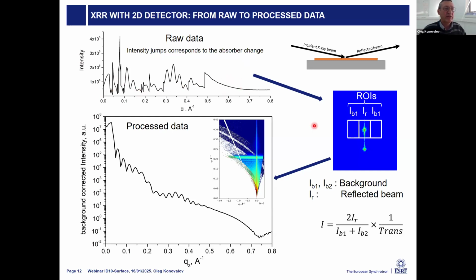And then at each point, we measure now with the two-dimensional detector. On this detector, you can see this is the rest of the direct beam, and this is the specular reflected beam. This is what we really want. Then we select several regions of interest, like 1 for the specular beam and 2 for the background. Through this formula, normalized on the attenuation of the filters, we can reconstruct the reflectivity profile. Everything is done almost at the same time at the beamline. After measurement, we can immediately run the scripts on Slurm, on the special machine we have at the beamline, and then you have all the needed data right after the measurements.